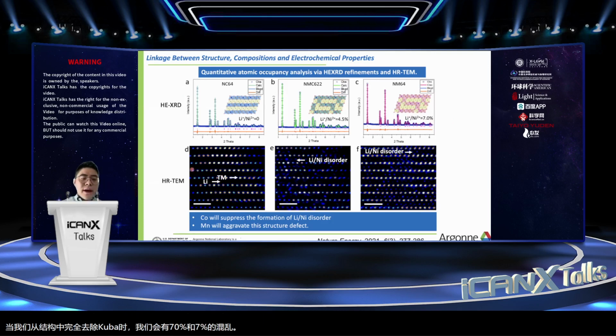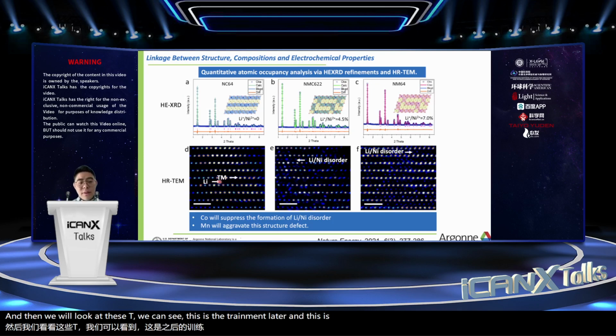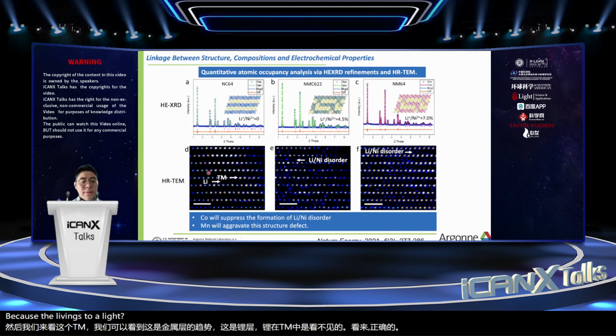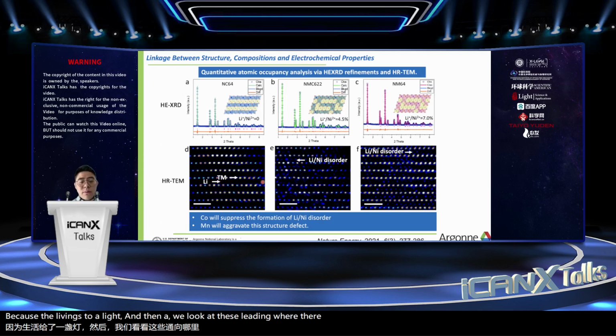And then here is the high resolution TEM. The bright spots are transition metals. And then we will look at this TEM. We can see this is the transition metal layer, and this is the lithium layer. Lithium is invisible in the TEM view, right? Because lithium is too light. And then when we look at the lithium layer, there are no transition metals.